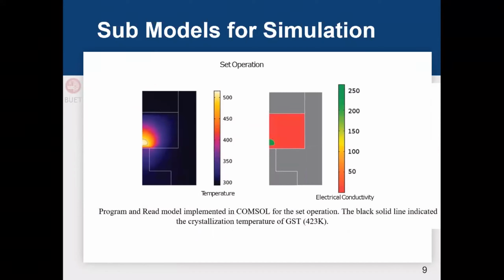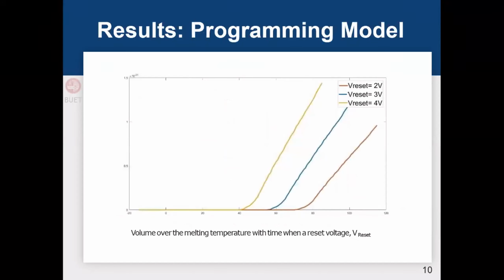And for the set operation, we can see that applying a different pulse technique, we can actually achieve temperature lower than 423 Kelvin, so it still stays in the crystalline state. That means a higher electrical conductivity level. In this curve, we can see that applying different amplitudes of voltage with different pulse techniques, we can actually get a different amount of volume that has a temperature over the melting temperature of GST. As the reset voltage value is increased from 2 volt to 4 volt, it requires fewer pulses for the GST to be converted into the amorphous state.